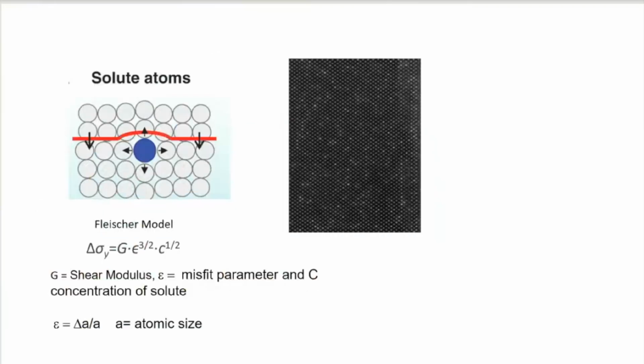We also have what is known as solid solution strengthening. And today you can see the atoms in solid solution, the bright spots in an aluminum solid solution image, which are the solutes. And a dislocation has difficulty passing through it because there is a strain around each solute because of the size misfit with the matrix atoms, and therefore it becomes a barrier for motion and therefore strengthens.